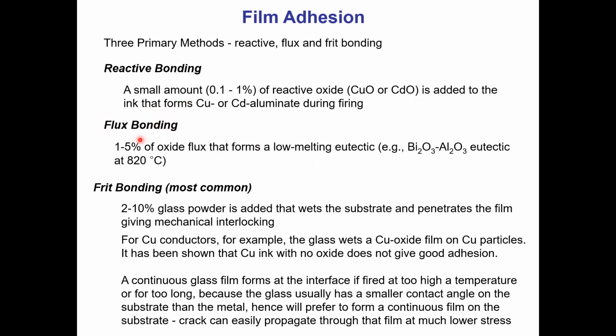Flux bonding is another approach where, again, a small fraction of the flux material like bismuth oxide is added as a flux to the ink. And then there is a eutectic, for example, between bismuth oxide and aluminum oxide at around 800 degrees C. So if you heat treat or fire the material around the eutectic temperature, you can actually make a eutectic melt that will create chemical bonding of the film with the substrate.